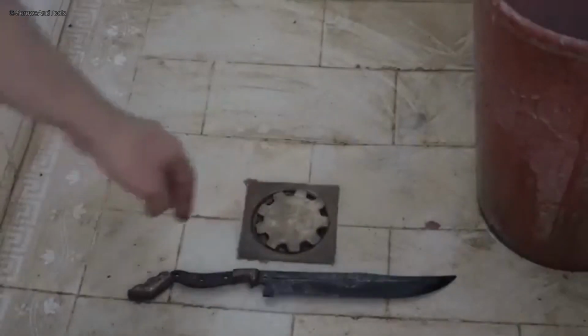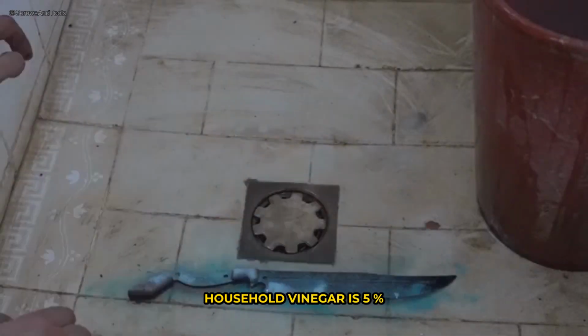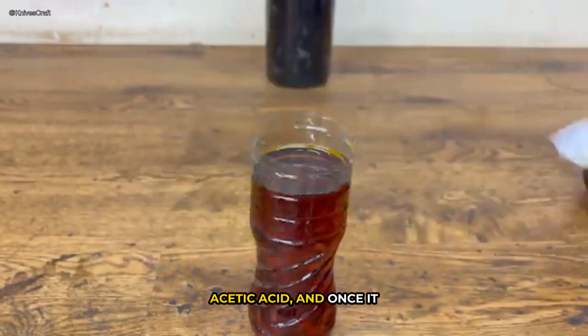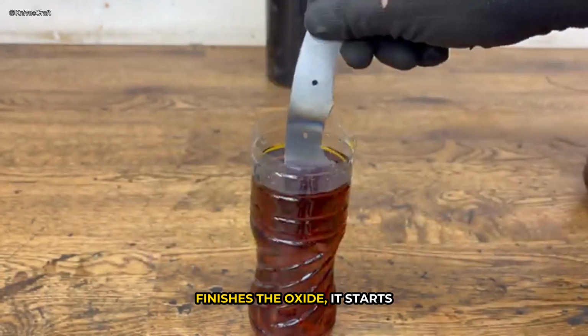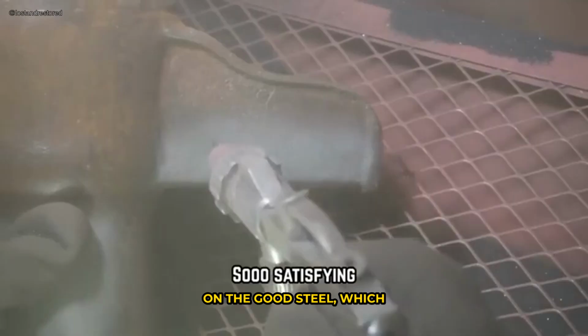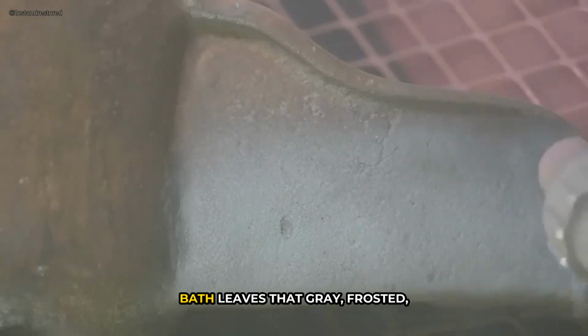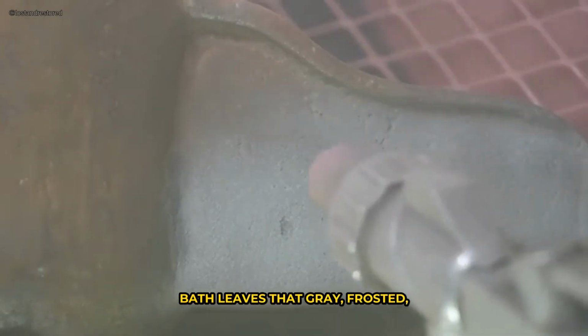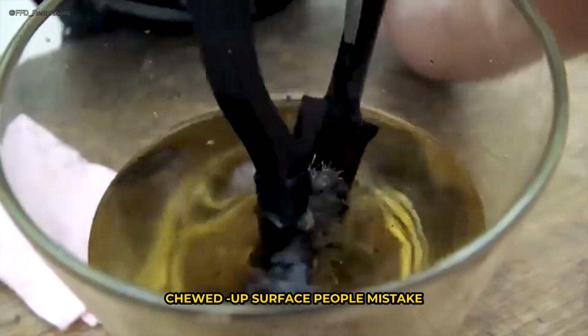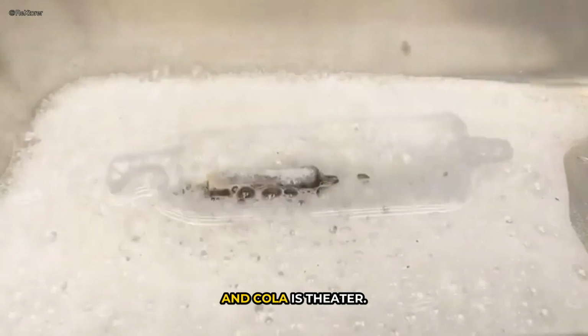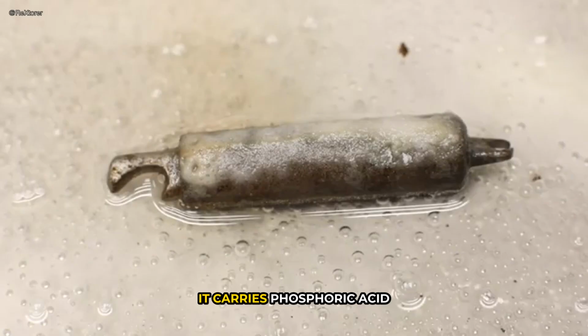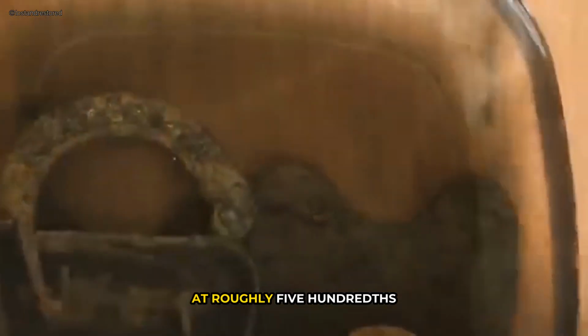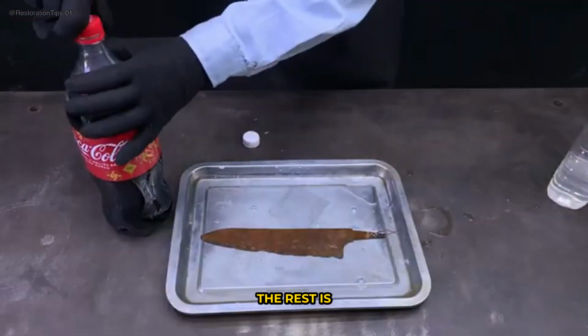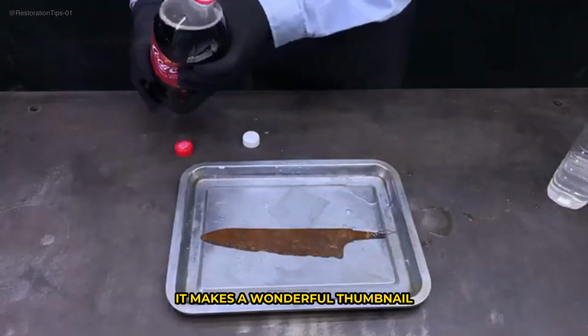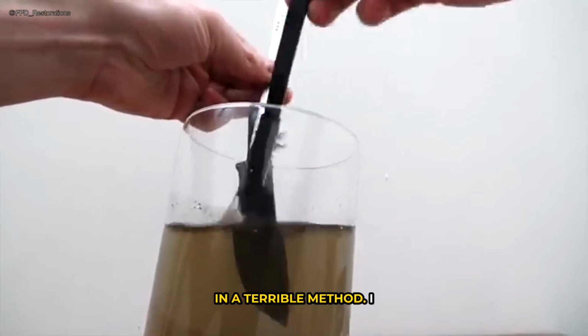Now the comparison. Household vinegar is 5% acetic acid, and once it finishes the oxide, it starts on the good steel, which is why an overnight vinegar bath leaves that gray, frosted, chewed-up surface people mistake for age. And cola is theater. It carries phosphoric acid at roughly 0.05%. The rest is sugar water. It makes a wonderful thumbnail in a terrible method.